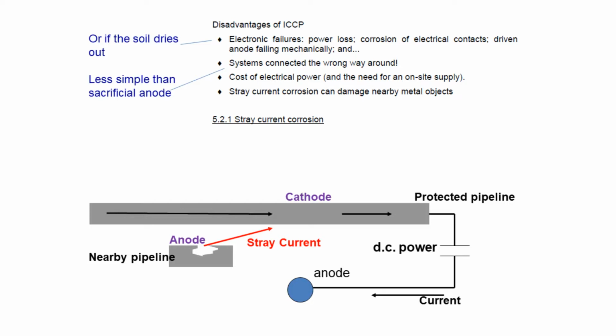Therefore, if you have a nearby non-protected pipeline in the ground, you may find that the ICCP system pulls some stray current from the non-protected pipeline. And that doesn't matter along most of the length of the non-protected pipeline, because that just involves electron flow along its length, but you have this unfortunate point where you have a jump from electron current to ion current through the ground. And remember, the protected pipeline is a net cathode, so the stray current as it jumps the gap from the non-protected pipeline does so by forming a net anode on the non-protected pipeline. In other words, you cause intense localized corrosion at the points where the non-protected pipeline passes in the ground near to the protected one.